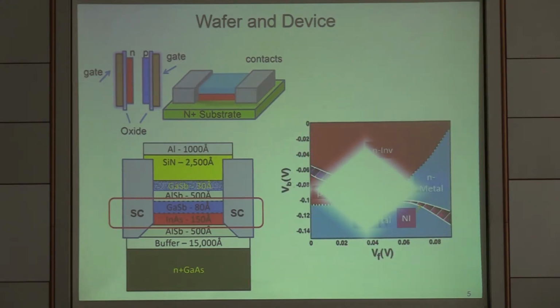So now if you have one substrate which is a doped substrate, it can be used as a backgate, and you put aluminum or other material as a top gate. So you have a double gate device to control the density of electrons and holes. And you can contact these to the outside by superconducting leads or by normal leads. So here's the phase diagram.